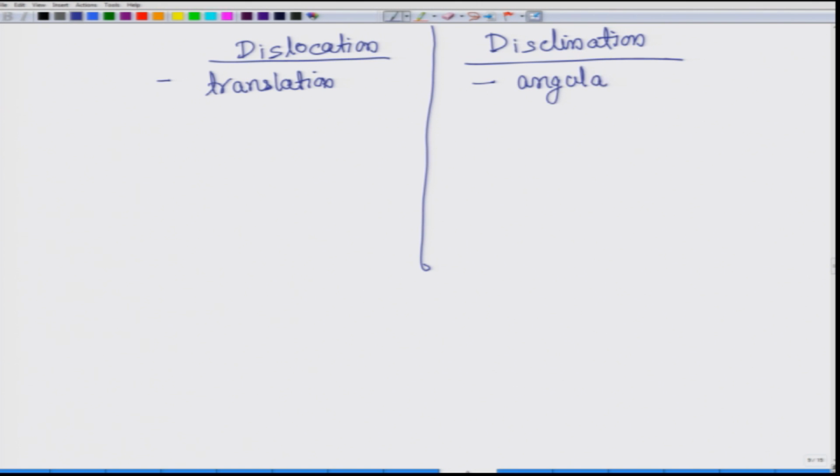So, this configuration leads to angular opening, which is what describes it as a disclination, but that is actually not the basic definition. If you look at it structure-wise, you would see that at long distances in dislocation the structure relaxes, which will not be possible if it is disclination.